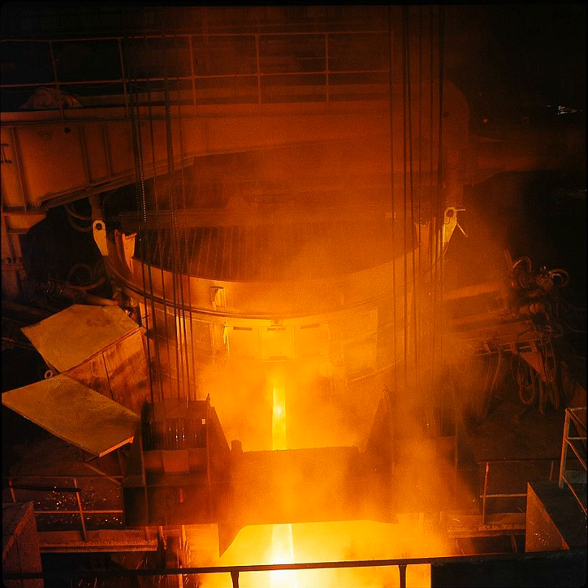During tapping, some alloy additions are introduced into the metal stream, and more lime is added on top of the ladle to begin building a new slag layer. Often, a few tons of liquid steel and slag is left in the furnace in order to form a hot heel, which helps preheat the next charge of scrap and accelerate its meltdown.